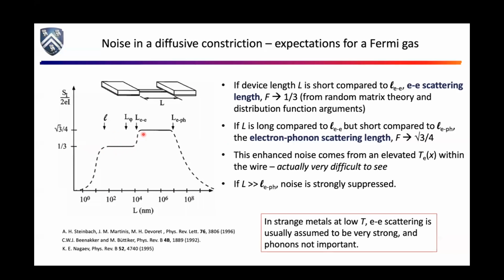If I let the electrons actually trade energy with each other, but still not talk to the lattice, the Fano factor goes up. The effective Fano factor should be √3/4, which is about 0.433. And then eventually, if my wire is really long and my electrons have a chance to talk to phonons, they cool themselves off and the noise is suppressed.